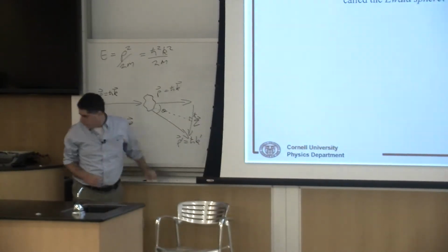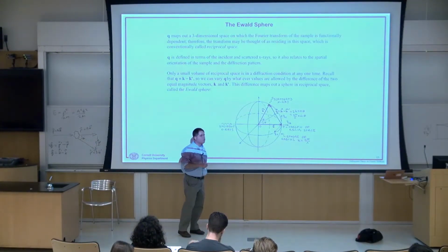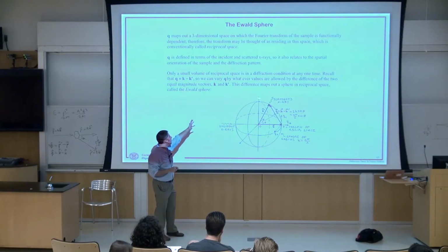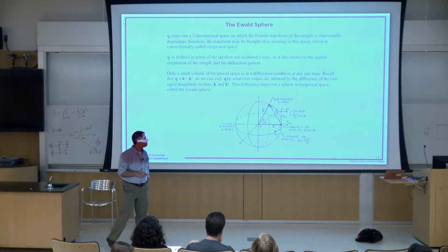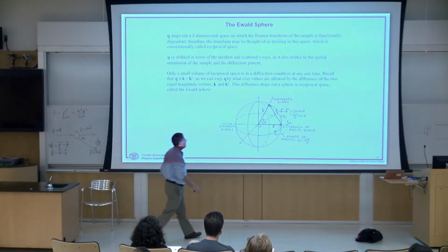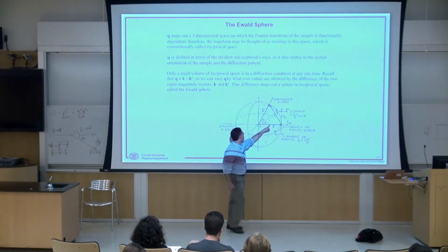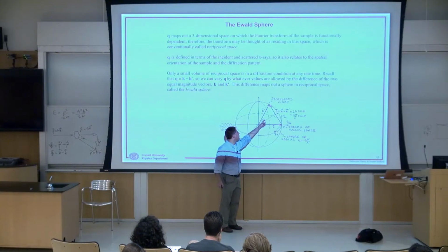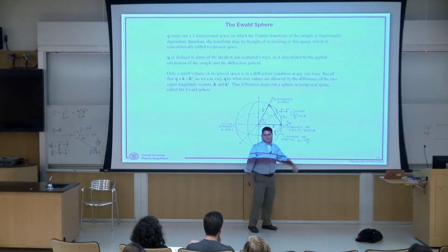So for elastic scattering, the length of the wave vector k is the same before scattering as after scattering, and therefore any possible allowed scattering event is only allowed to be on this shell. The momentum transfer over here, Q, is k minus k prime, which is 2k sine theta. You have to watch out for this particular definition. I would have defined this whole thing as theta, and this as theta over 2. But this is the physics definition, as you can tell from the annoying 4 pi stuck in the front. The crystallography definition would just be 2 pi over lambda.